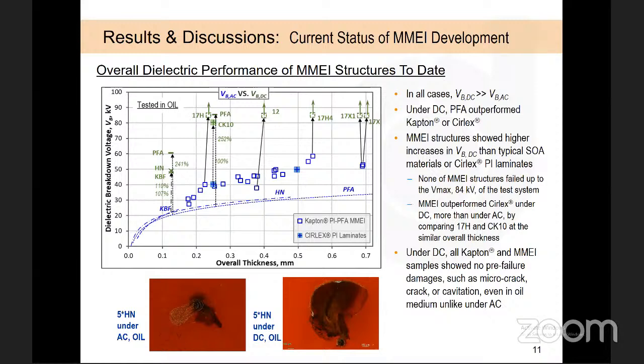The data I presented so far were from 60 Hz AC, but with DC, VB was much higher in all material types, but MMEI showed the greatest increases than any other materials, including Cirlex. Besides, under DC, the Kapton material showed no pre-failure damages, such as microcracks, unlike under AC, and this might be related with the lesser increase in VB than PFA.